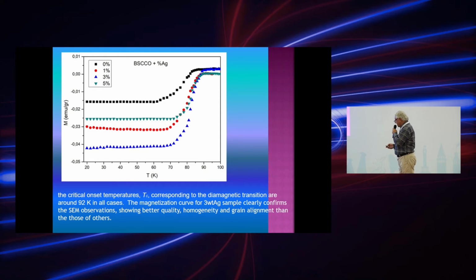We have measured magnetization. This is the field-cooled magnetization for the samples shown here. I would like to show the onset temperatures of the samples, around 92 Kelvin in all cases, but the pristine sample is a little bit lower than the substituted and silver-added ones. The magnetization curves for the 3% silver samples clearly confirm our SEM observation, showing better quality, homogeneity, and grain alignment compared to the other inclusions.